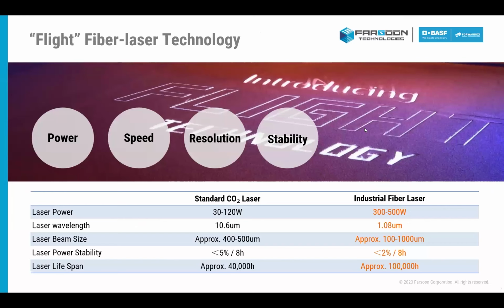So taking a look at Flight fiber laser technology compared to standard CO2 laser platforms that you would see on the market today. We can see a couple key differences. The first key difference is laser beam spot size. Traditionally in a CO2 SLS system, they use a laser with a spot size between 400 and 500 microns. This usually restricts our minimum feature size to about 1 millimeter, or about twice the size of the laser spot size. We can see though, with a fiber laser, we can get down to around 100 microns and the contour or outline pass to get real fine feature details, around 0.3 millimeters. But we're also able to open up the fill pass to 1,000 microns to decrease build times and scan times.